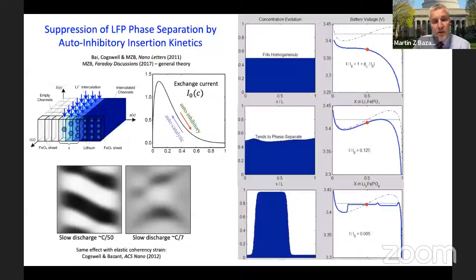And so let me now show you some movies of what those models predict. This is actually pretty old work going back to 2011. If you take this crystal, lithium iron phosphate, like I showed you before, we were originally viewing that crystal from above. And as you see in this cartoon, this material can be made in thin little platelets. And in the depth direction, we argue that there are very small gradients. There's fast transport and suppressed phase separation in the depth. So it's almost like a 2D system when you look from above. Or if you take a slice of it, it's a 1D system.